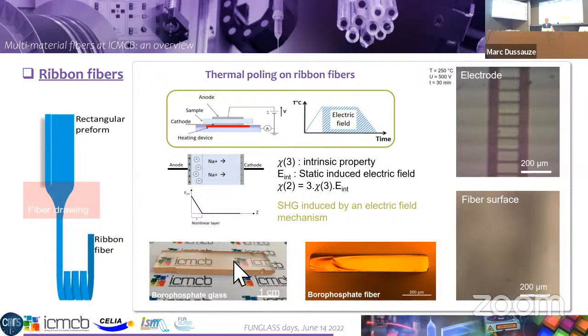And we see that actually this is something that is now developed well and works well in the group. This is George, who is doing that with us as a PhD. So here is an example of borophosphate preform, which is optically polished and then transferred into the fibers. As we see, we have a ratio of something like 1:10, which is enough for many applications. And we have some widths that can go up to 2 or even 3 millimeters, which is quite large enough for many applications.